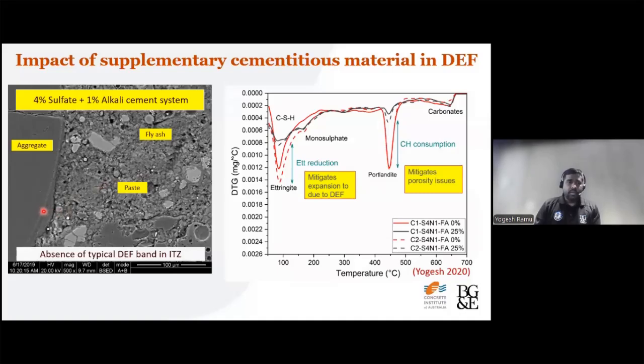One thing is it doesn't have DEF in the system, and another benefit is, if you can see here, the red graphs are the mixes without fly ash, and the black ones are mixes with 25% fly ash. You can see that the Portlandite peak is higher for zero fly ash mixes, and for 25% fly ash mixes it is almost nothing. What is happening is the reactive silica in the fly ash consumes this Portlandite to form additional calcium silicate hydrate, which is a denser, more impermeable and strength-giving cement hydrate in the concrete system.